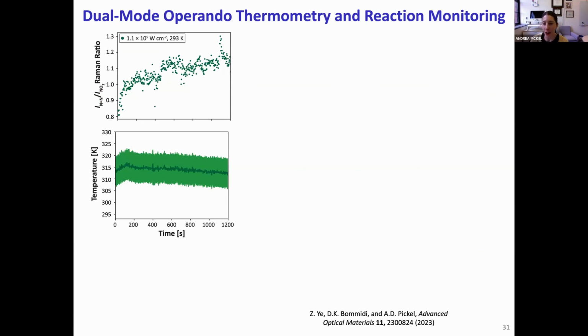To quantify the reaction progress, we use the intensity ratio of a Raman peak associated with the product versus a peak associated with the reactant. So we see that the Raman ratio initially increases as the reaction progresses and then saturates towards a constant value. Meanwhile, the temperature is roughly constant during the measurement period, which is expected since we estimate the initial transient heating to be many orders of magnitude faster than our integration time. So this is representative data for one excitation intensity.